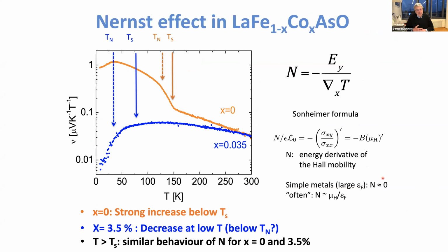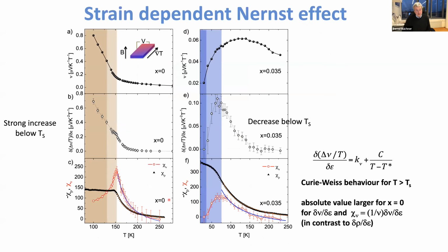The Nernst effect is even more complicated in some sense because in simple metals, the Nernst effect is always 0. And some of you might remember all the discussions on the cuprates on the reason of the Nernst effect, which I will not solve. So the Nernst effect is the energy derivative of the Hall mobility. And here you see the parent compound and the doped compound, very much different in the ordered phases, but at high temperatures rather similar. And also for the Nernst effect, we can follow this change as a function of strain, which for me was a real surprise. That really tells us that details of this Fermi surface are extremely strongly dependent on details of the lattice.